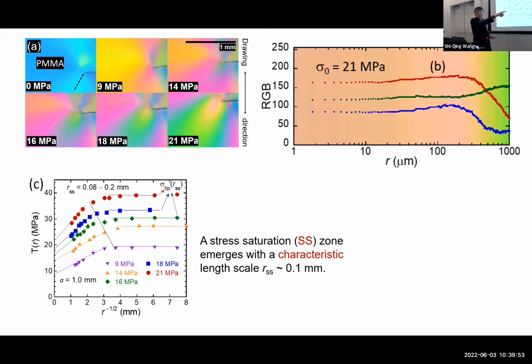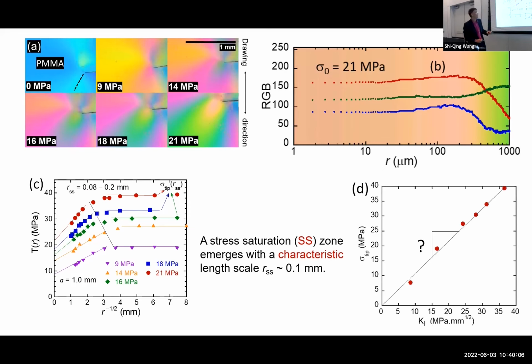You do exactly the same for window glass. This cutoff will be 1 nanometer, impossible to resolve. But for polymer, it was resolvable. And quite interesting, it's very different from traditional fracture mechanics. The tip stress builds as I load more and more. Linearly, tip stress grows with the loading parameter, the so-called stress intensity factor, linearly.